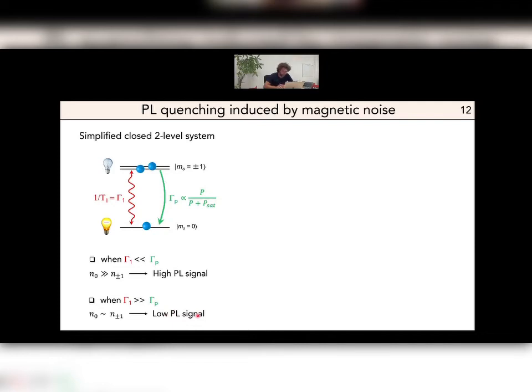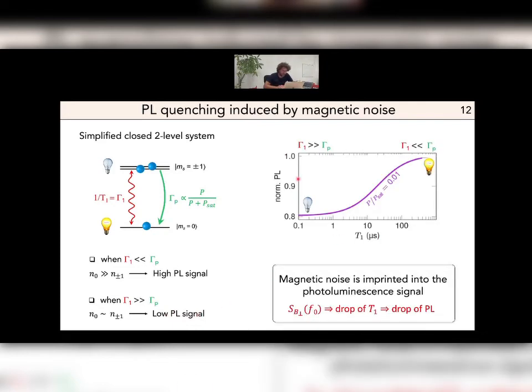So if you make the calculation, then you can see that you plot the photoluminescence as a function of T1, you can see that indeed, when T1 is decreased, or gamma 1 increases, you have a drop of the photoluminescence by something like 20%. And of course, if you increase the optical laser power, you increase gamma p here, so the position where you can see the drop in photoluminescence is shifted towards lower values of T1.